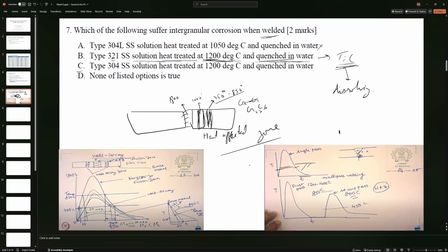Here you'll have a region which will go up to maybe 1000 degrees Celsius, and it'll cool down slowly. The region of formation of titanium carbide is above the chromium carbide temperature range. So if we are cooling the sample down from say 800, 700 or 1000 degrees, then first initially the titanium carbide should form, and then...